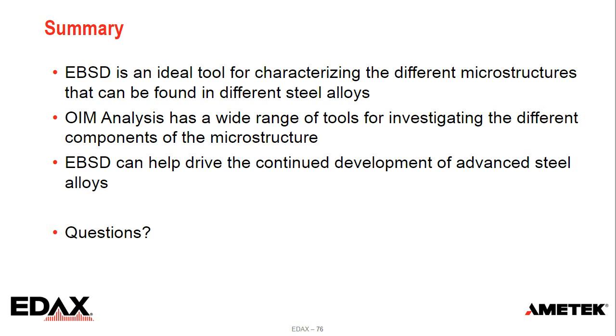So there's a question here. It says, I had problems detecting retained austenite, and we tried transmission EBSD or TKD, which yields much better results. Yeah, and I had mentioned transmission EBSD. That's an approach where we use a thin foil and look at the sample in transmission rather than reflection. Because of that, our interaction volume is minimized and we can get much better spatial resolution. Exactly, you can certainly improve spatial resolution that way.